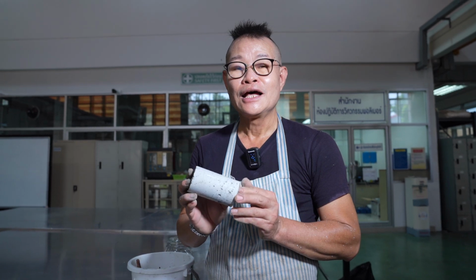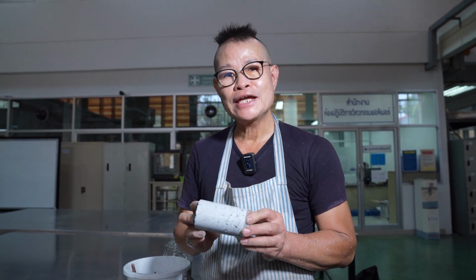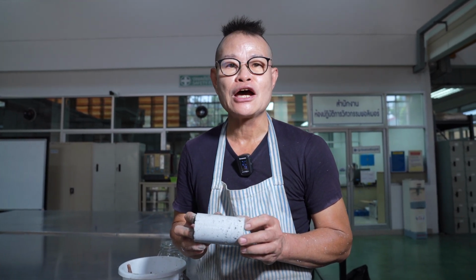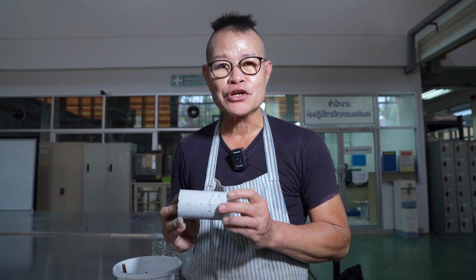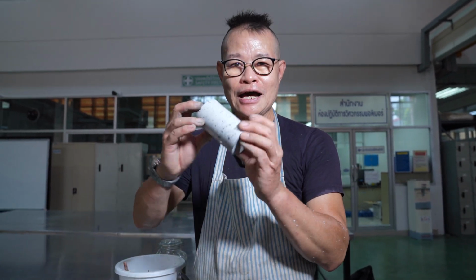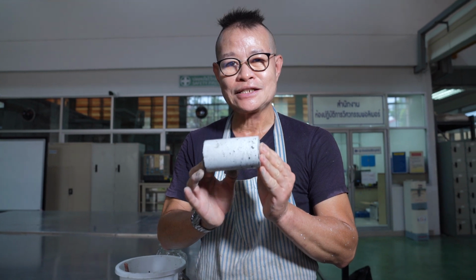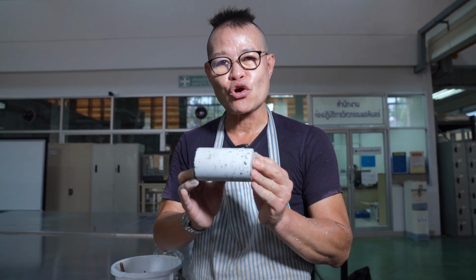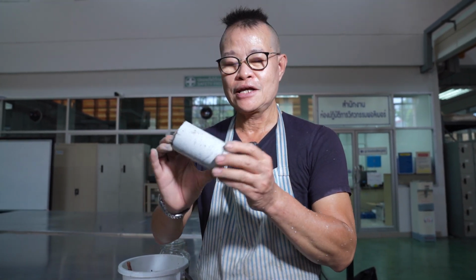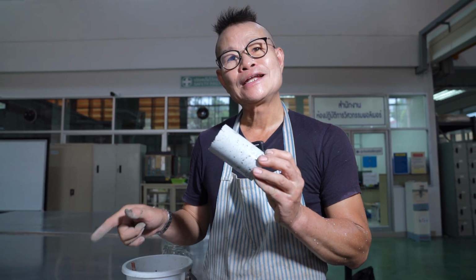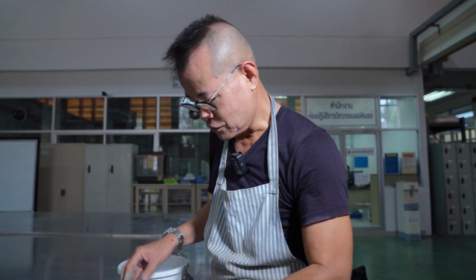After 7 days of curing at room temperature, or 2 or 3 days of curing at 50 degrees Celsius, we can have a very solid and very strong concrete block from that lightweight engineered aggregate, right?